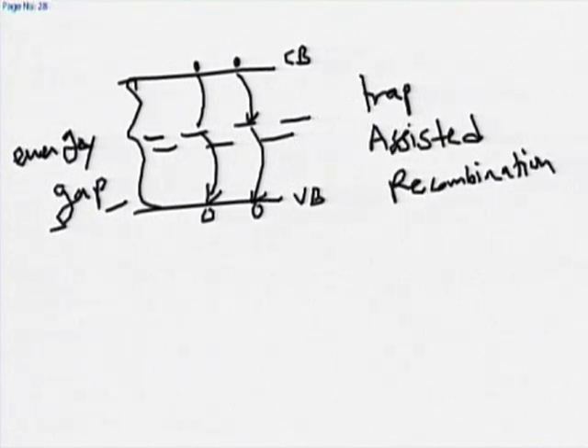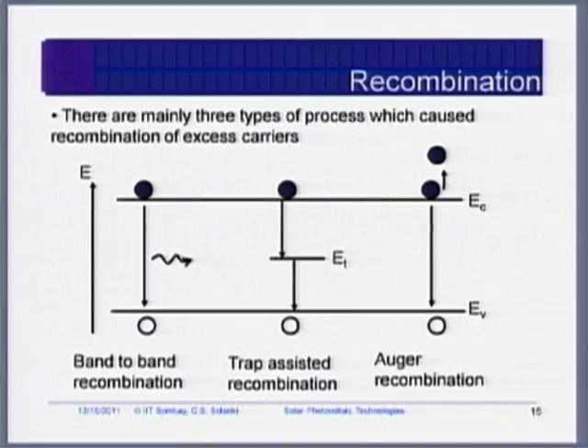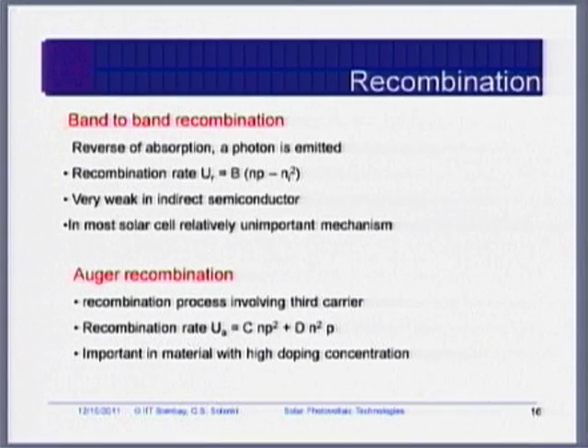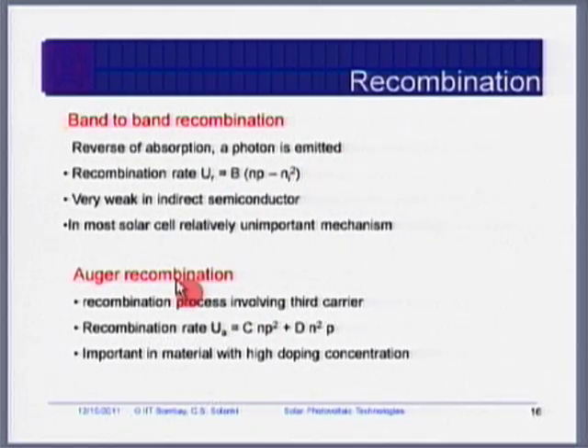Because the concentration of these impurities and defects is not high, the energy levels are isolated, not continuous. Recombination of electrons takes place via these energy levels — this is called trap-assisted recombination. This is the most common recombination in solar cells and is what scientists worry about all the time.